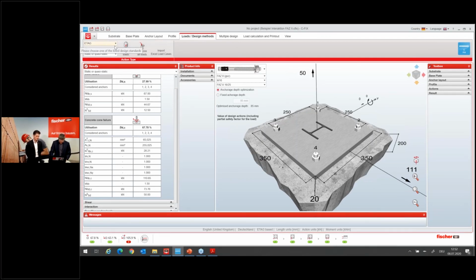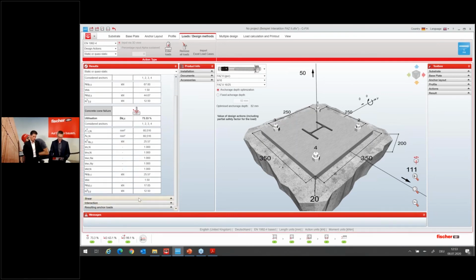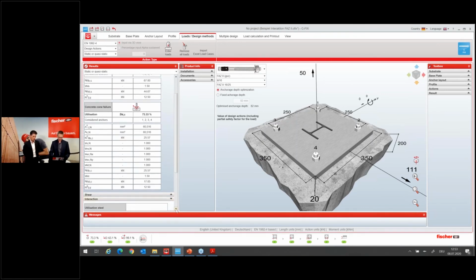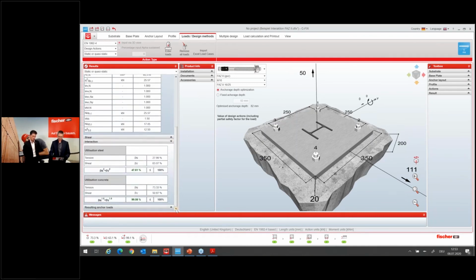Design is currently ETAC design. If you look here to the utilization degree, the situation is overloaded by roughly 6%. If you change now back to EN 1992-4, then you'll see that the utilization degree decreases to below 100%, and you can realize this application in practice. And this is due to the fact that the interaction equation is performed now in the future always with the 2 design proofs, one for steel failure and one for the other failure mode, which you see also here in the details of the results.